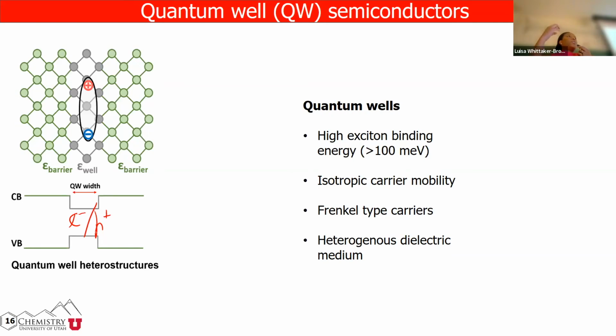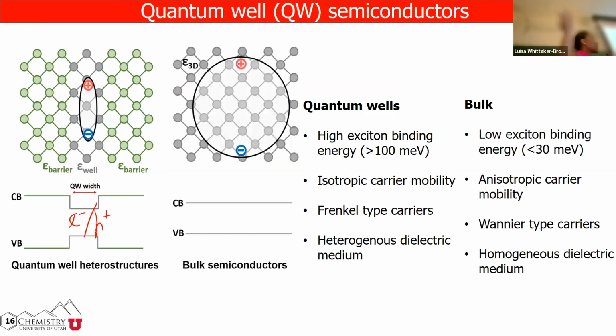Then you have a heterogeneous dielectric medium because of the dielectric mismatch between the two layers. Compared to bulk silicon, for example, where you just have electrons that are excited, you have mainly free carriers because the exciton binding energy is very close to thermal energy. So then carrier mobility is anisotropic. You have Wannier-type carriers, basically free carriers, and it's a homogeneous dielectric medium.